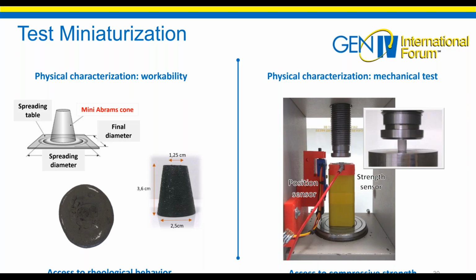It consists of filling a cone with the cement paste and then lifting it. Once the cement paste has spread, the spreading diameter is measured in two orthogonal directions. The relative spread is defined as the ratio of the spreading diameters to the largest diameter of the cone. For future use, it has been defined that the relative spread should be greater than 2.5. My results show that the significant impact is due to the physico-chemical properties of the powder added, like the specific surface. This specific surface plays a key role in the water demand and in the rheology of the cement paste.